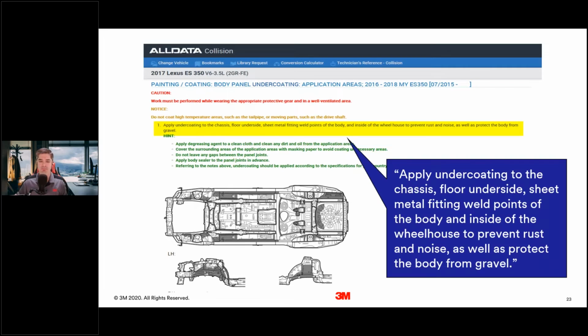Toyota here again, they're highlighting and telling us these areas of the vehicle that need to have undercoating put on there in the event that we're doing any repairs, right? And you can see here by the rear around that floor pan, that front edge of that floor pan, that's a critical component that gets a lot of road wash and salt and rocks hitting it. You'll see that only one floor extension is actually coated and not the other. And that's simply because there's an exhaust that comes out on that other side. So there's an exhaust there that they don't need to be putting any coatings on. They need to just have the heat shields up underneath there. And so they don't want undercoatings in those locations. It's important to point that out.